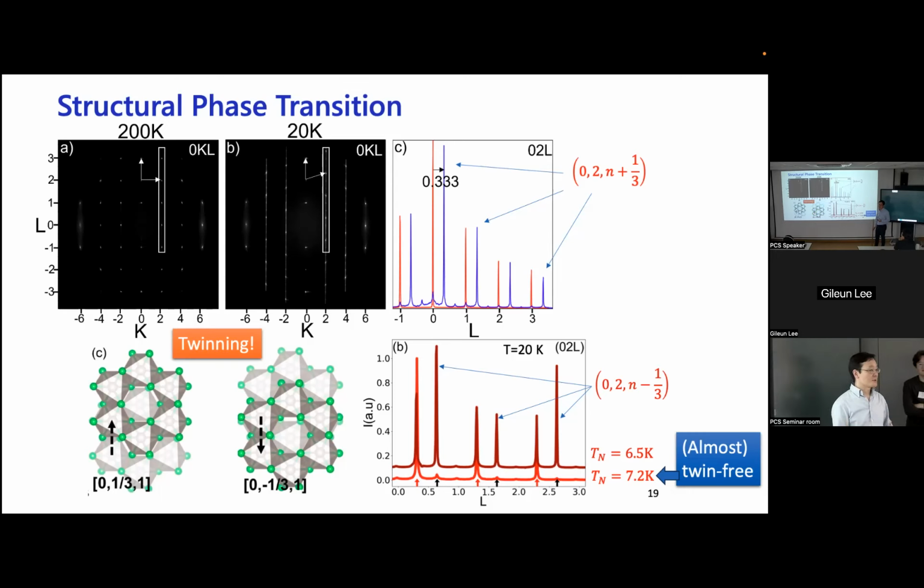You cannot have a perfect crystal, so it's a possibility. But mostly we're trying to think of this as stacking-related defects and stacking-related disorder rather than what might be happening in the plane. If there's an in-plane defect, it might be responsible for nucleating the twinning, so then it would be reproducible even though the heating and cooling cycle is repeated.